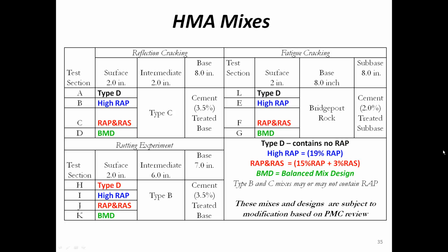Well, and I would also encourage you in your laboratory testing plan to take a look at doing some additional overlay tester testing using very, very small gaps, very small deformation or displacement levels in the device, because if you're not using extremely high strain rates on your test sections, because you shouldn't on your test sections, then that's going to be the source of a huge disconnect between what you observe in your test sections and what the overlay tester predicts in the laboratory. Yes, I'm sure you're right.